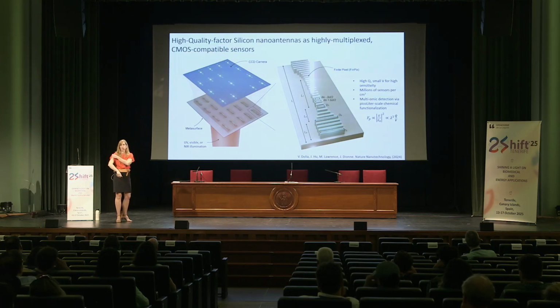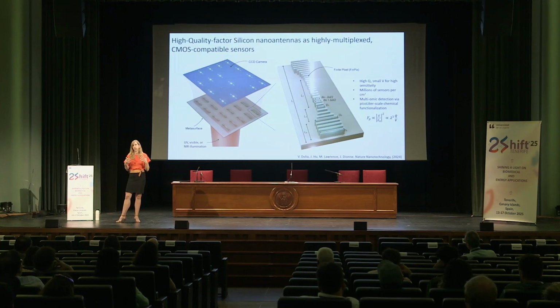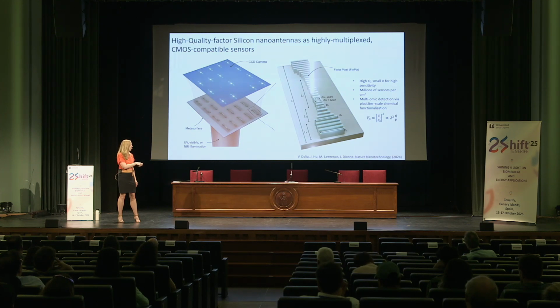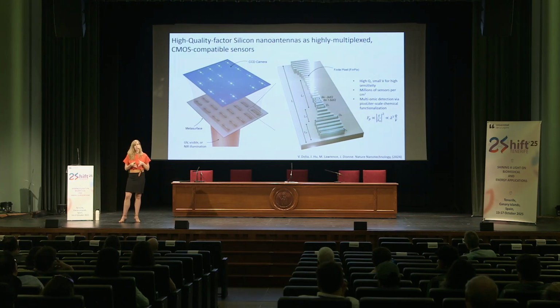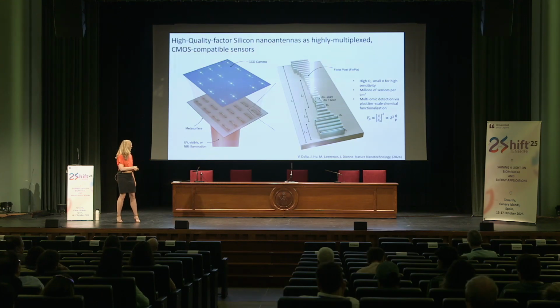Well, the Purcell factor, which basically governs the efficiency of dipole emission or Raman scattering, is directly proportional to your electric field enhancement squared, which is also proportional to the wavelength cubed times the quality factor divided by the mode volume. So generally, it's been thought, well, you can either boost Q or decrease V. In our case, we actually try to do both. So we try to get high quality factors and small mode volumes to get the highest possible Purcell factors.